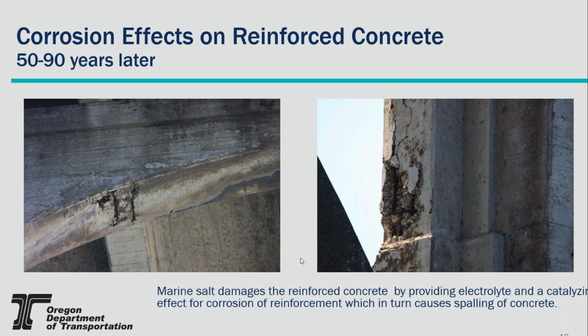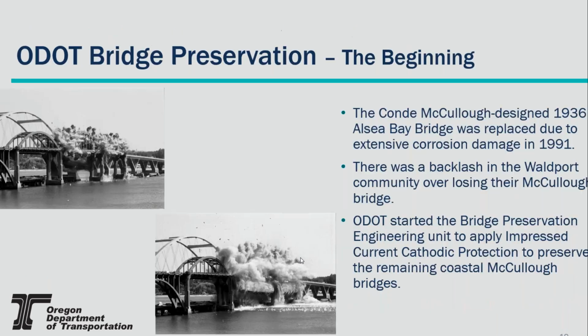So that effect led to what you see here. During the decade of the 1980s, the Alsea Bay Bridge in particular started to show its age, and it had a lot of spalling concrete issues. There were periods when ODOT tried to basically prevent boats from being under the bridge to keep falling things from hitting them. They went through a period of trying to scale the bridge on a regular cycle. Nothing was really satisfactory, and so they determined that they needed to replace the bridge. And it was replaced.